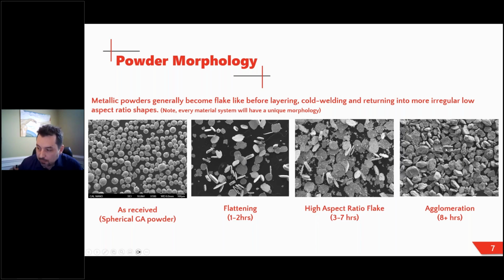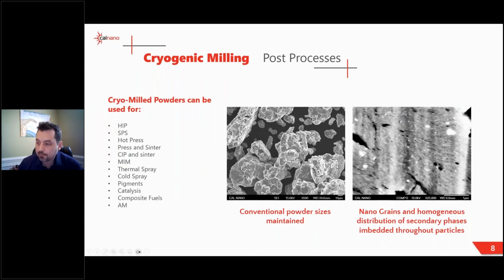And in this case, we're actually keeping it a conventional size, which is an important point. So even though we are a nanotechnology company, we can control, when desired, the microstructure. So here's a piece of one of these powders that's been cross-sectioned. And we can see that we have a very refined grain structure into the nanoscale, as well as these hard phases that have been introduced, in this case, aluminum oxide inside of an aluminum matrix. And so we have a very uniform distribution of nano particulates, nano grains, but the particle sizes are conventional in the several microns, 5 to 80 microns in this case.